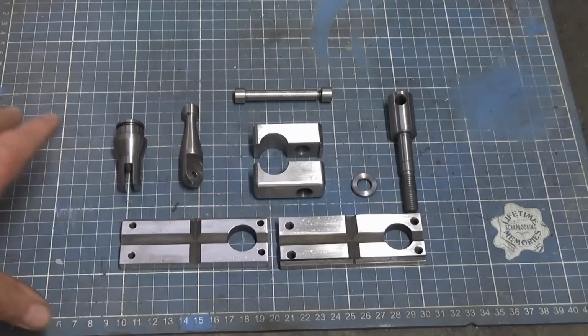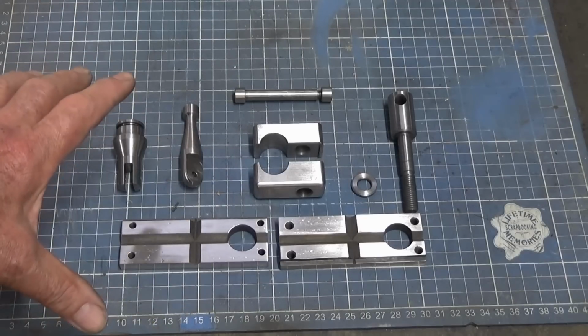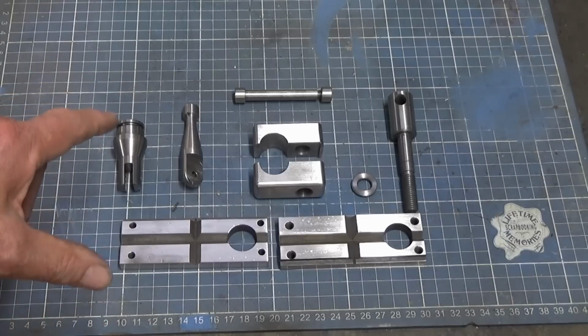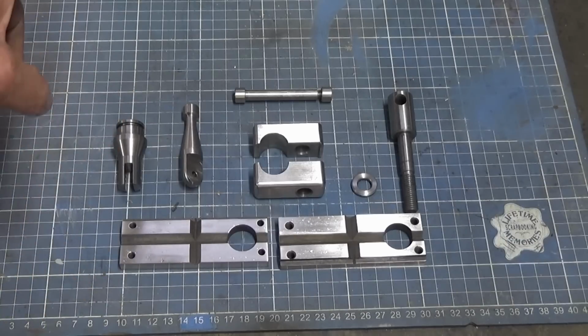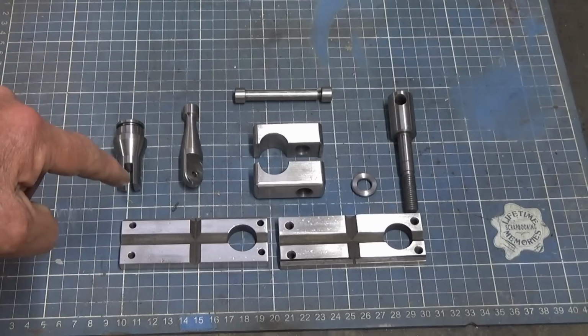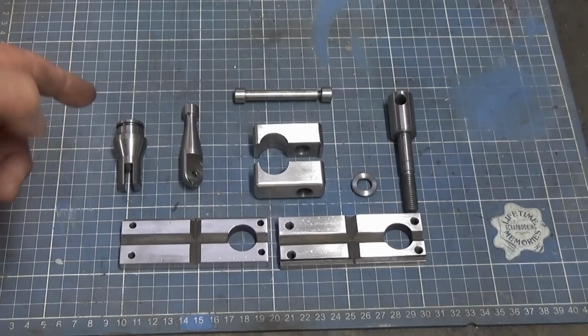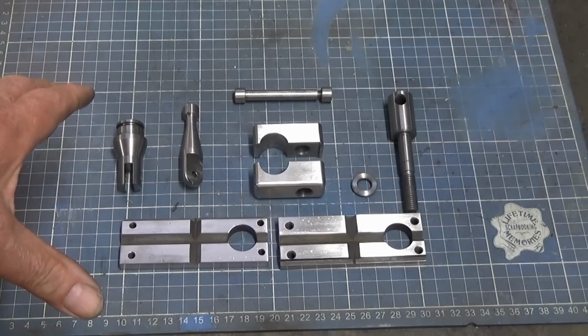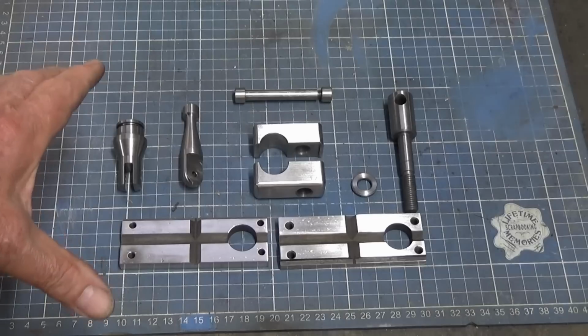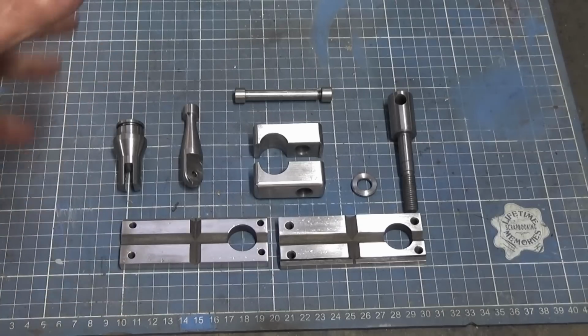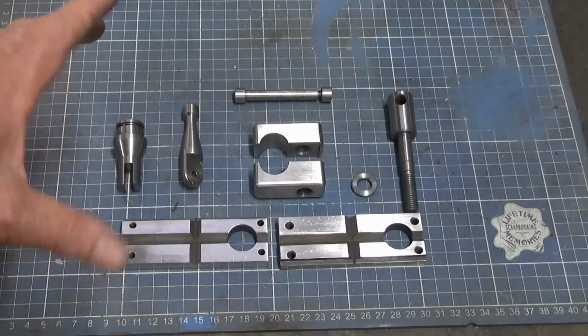And all I've done to this point is I've sanded the surfaces to make sure there's no machining marks in them. And what we're going to do now is put them through the ultrasonic cleaner. We'll do that in batches. And it doesn't matter what sort of metal finishing process you're doing, that's usually the first step. So it doesn't matter whether it's anodizing or zinc plating or parkerizing, you have to start with super clean metal.